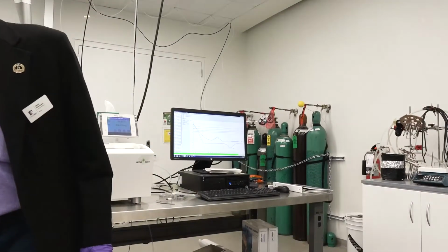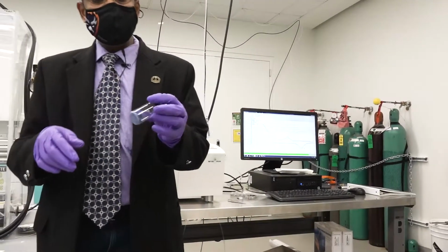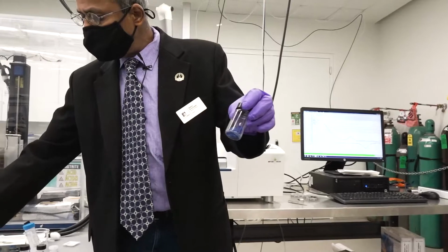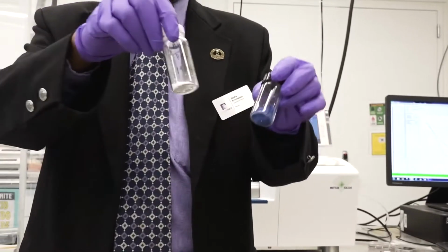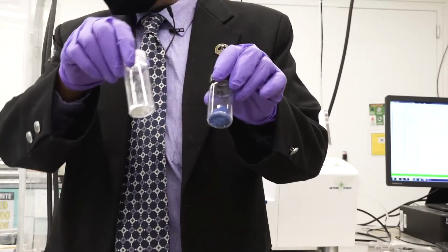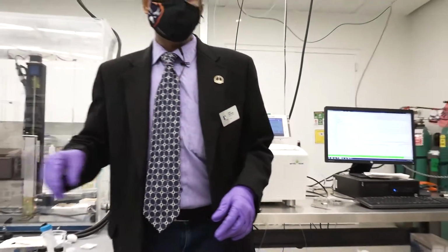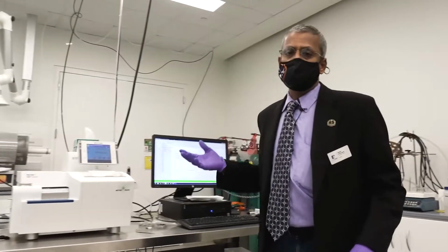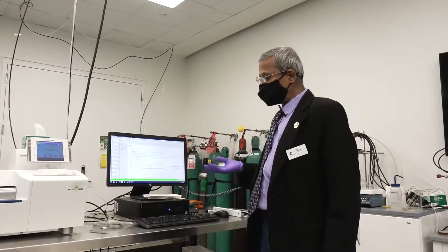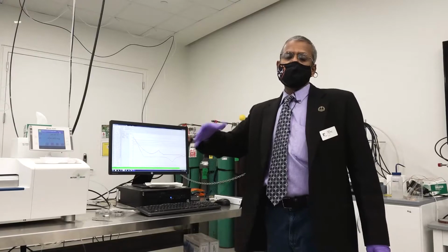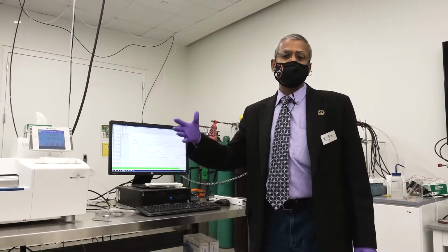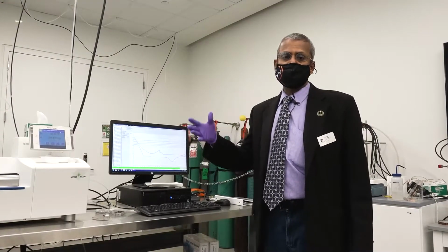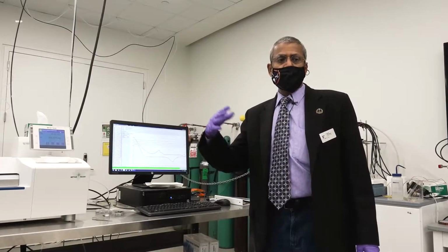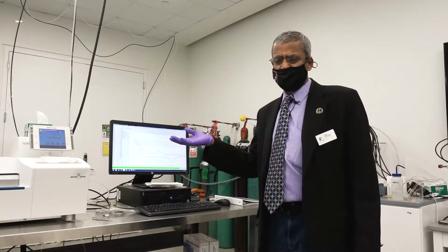We have many samples which we try to understand the chemistry. This is an encapsulated material. This is a titanium dioxide doped with eicosane. So many samples we tried and then tried to understand the thermal analysis and differential scanning calorimetric analysis about what is the transition, phase transition due to latent heat transition or phase transition due to the chemical bond breaking and making of a chemical structure.